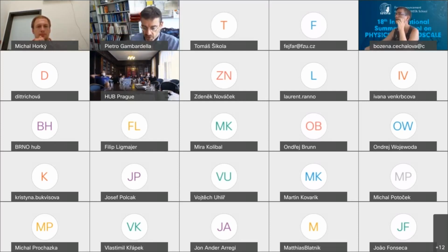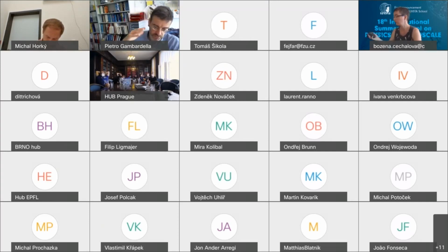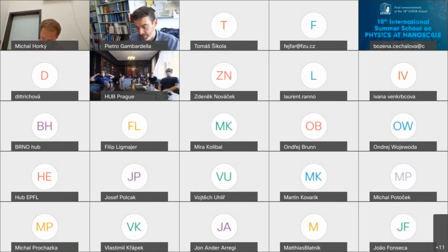Otherwise you have back diffusion of spins from the interfaces, and the spin currents cancel each other. So it is typically considered that one needs a minimum thickness of platinum of around 3-4 nanometers in order to achieve a full spin accumulation. We actually think that in platinum alone, this should be larger, of the order of 10 nanometers, but this is debated.